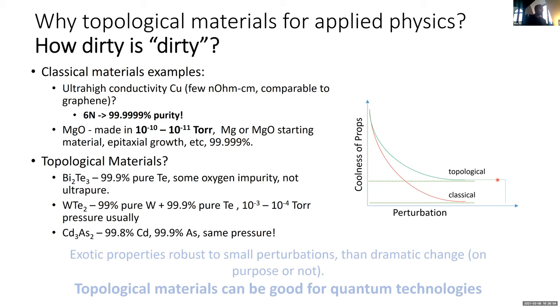So the exotic properties in topological materials are robust. This is why we say they're topologically protected. Until you break that symmetry that held those special features together, the properties stick around. And then when they break, they suddenly break. You lose it in a relatively all at once fashion. And so this type of behavior is very good for technology, for quantum technology.